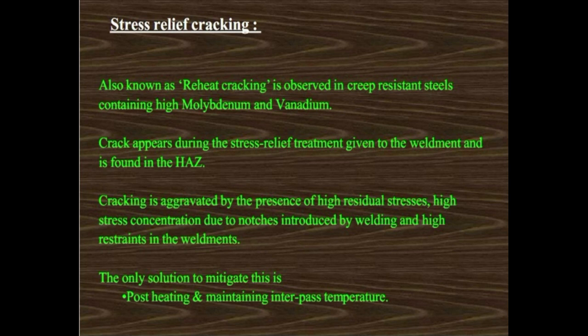Stress relief cracking, also known as reheat cracking, is observed in creep-resistant steels containing high molybdenum and vanadium. Cracks appear during the stress relief heat treatment given to the weldment and are found in the HAZ. Stress relief cracking is aggravated by high residual stress and high stress concentration due to notches induced by welding and high restraints in the weldments. The solution is post heating and maintaining the correct interpass temperature.